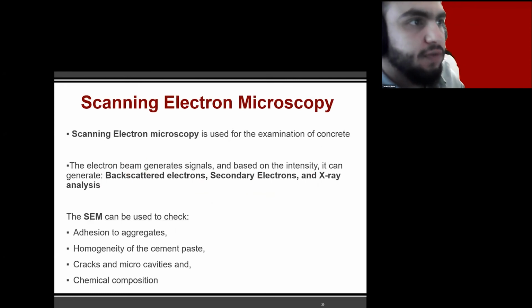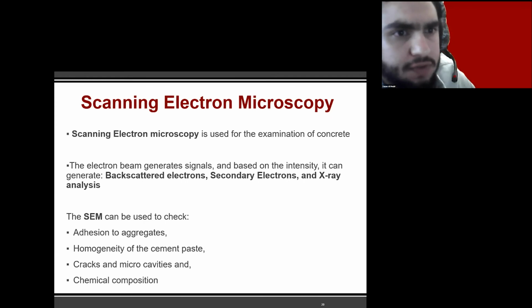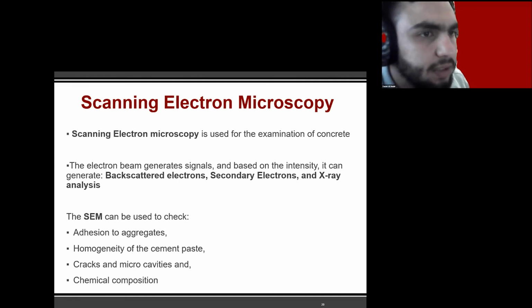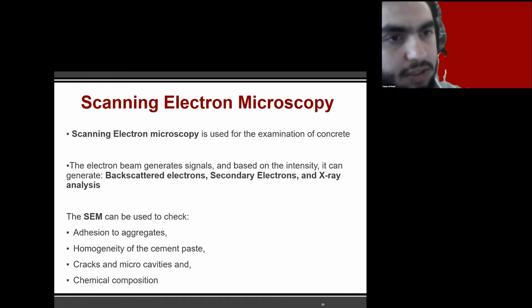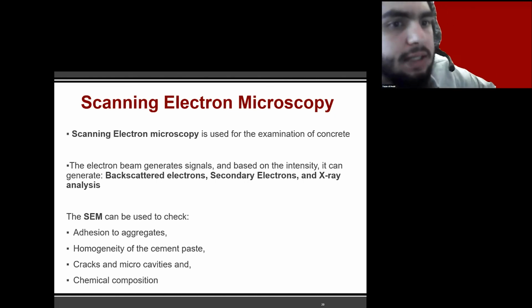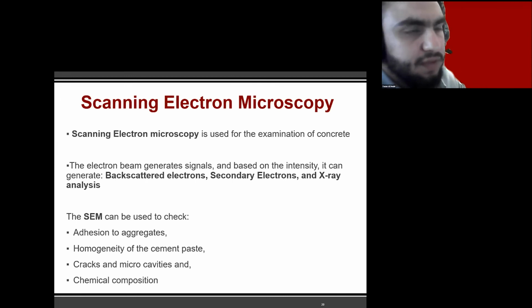Another test that was performed was the scanning electron microscope, which is a very powerful and useful tool that was used in this research on the concrete samples to check several aspects such as the cracks and cavities present, the chemical composition of concrete, the homogeneity of cement paste, and the adhesion between aggregates and cement. Several SEM images were taken and analyzed where the microstructure was examined, focusing on evaluating the interfacial transition zone of different samples.